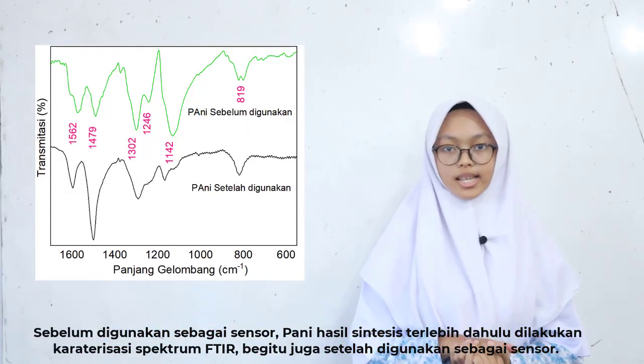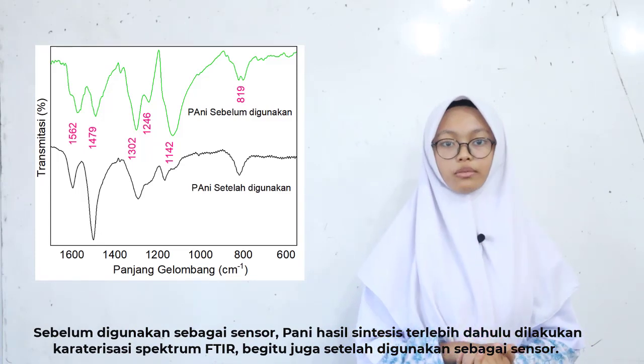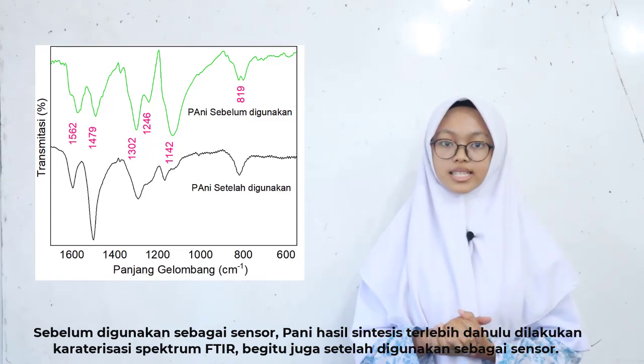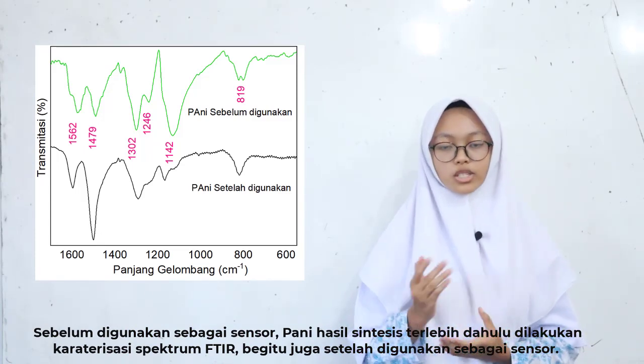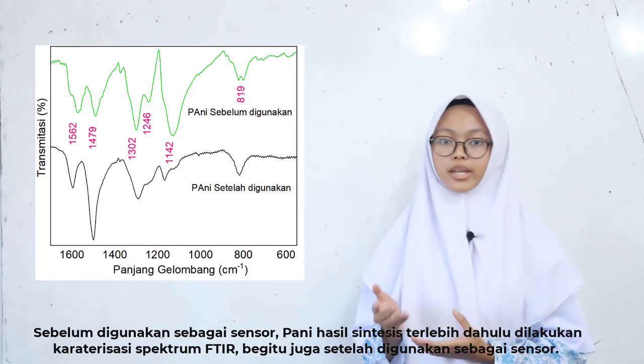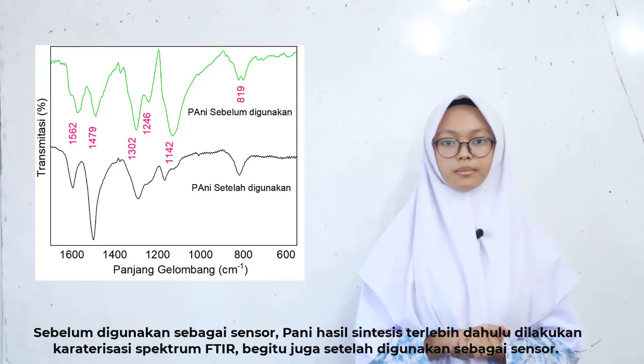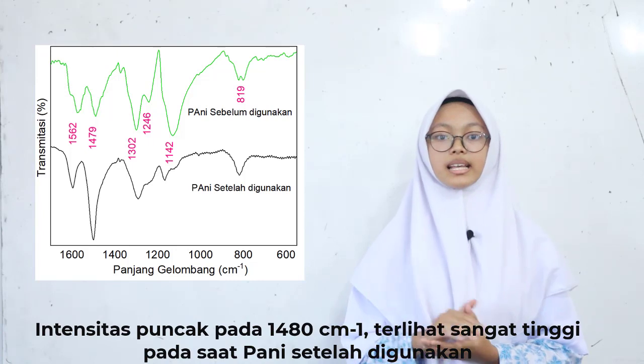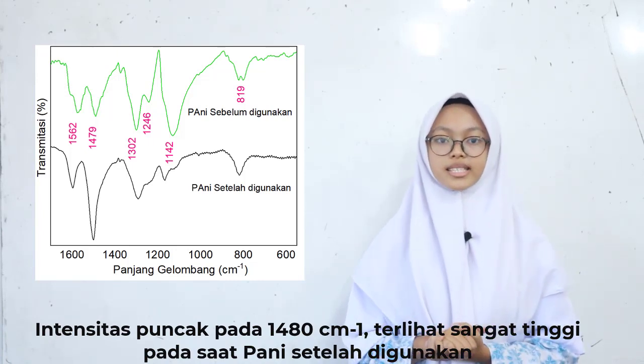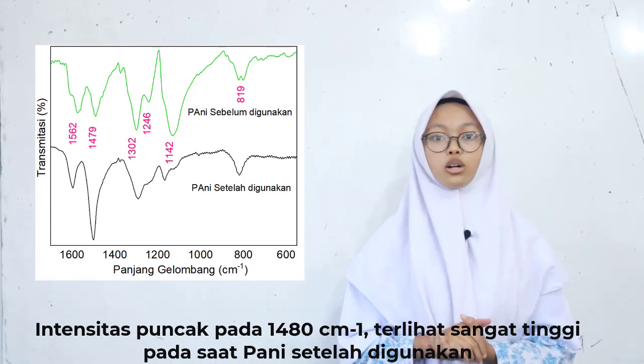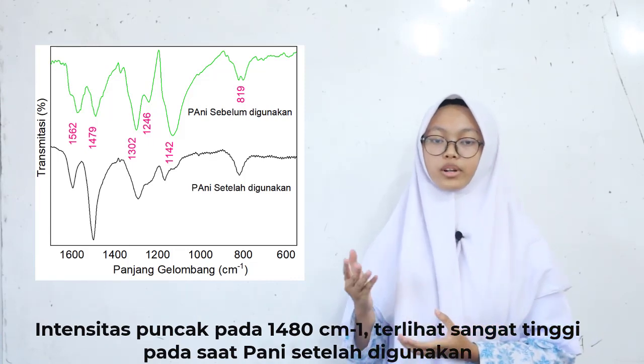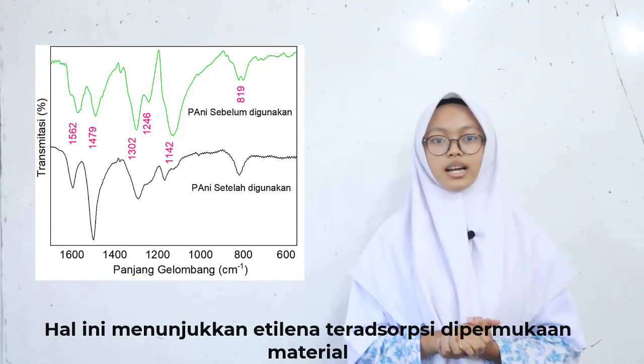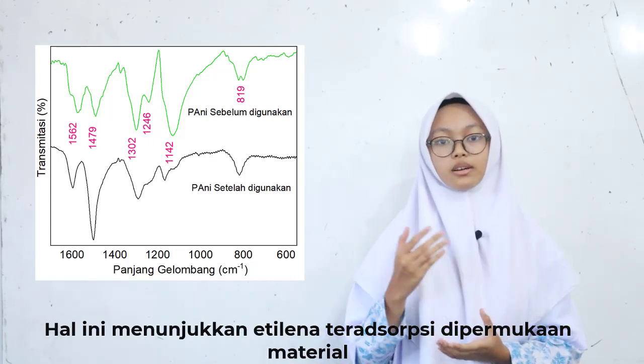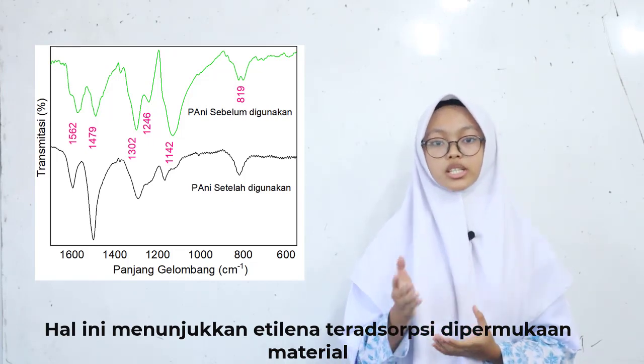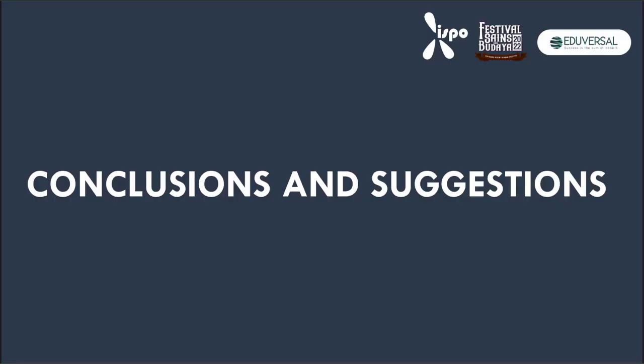Before use as a sensor, the polyaniline synthesis result was first characterized by FTIR spectrum, as well as after being used as a sensor. Peak intensity at 1480 cm^-1 looks very high for the polyaniline after use. This shows two possibilities. The first, ethylene is adsorbed on the surface of the material.